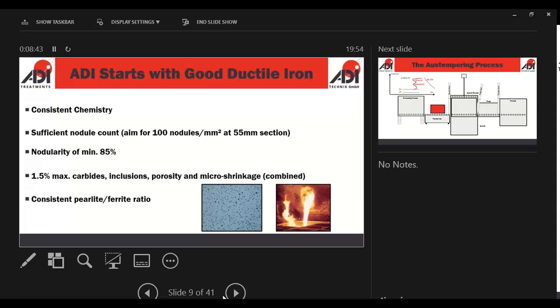We like a good nodule count. We aim for around about a minimum of about 100 nodules per square millimeter. Obviously, again, we understand with foundries, as you know, due to the cooling characteristics of castings and the section thicknesses, nodule count varies both with regard to size and with number. But we obviously are always looking to get the good nodules and good nodule count. Good nodularity is important. And this is obviously common sense when you're producing a good nodular or ductile iron. There's no point producing a nodular iron with 50% nodules in it. That's not really a good nodular iron. So we again look for a nodularity around 85% plus.